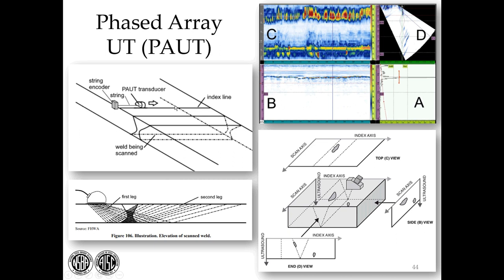I show it out here in the middle to start at one end, go across. This string keeps track of where the transducer is as you scan. That's called encoding. D1.5 requires that when you do phased array UT, you use an encoder. You can do it without it, but by using an encoder, you get a permanent record of the entire scan of the weld. This happens to be a snapshot of a weld at one particular index point. This is the width of the weld, and this particular image is at this point on the weld. And you'll see at that point in the weld, we also are getting a spike